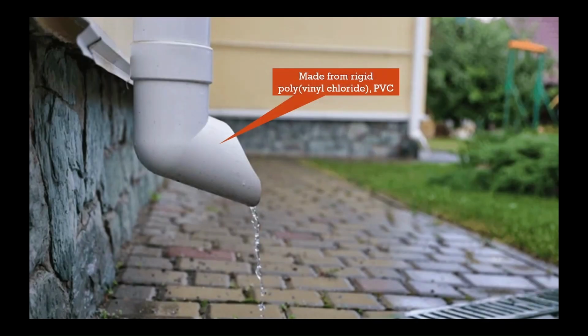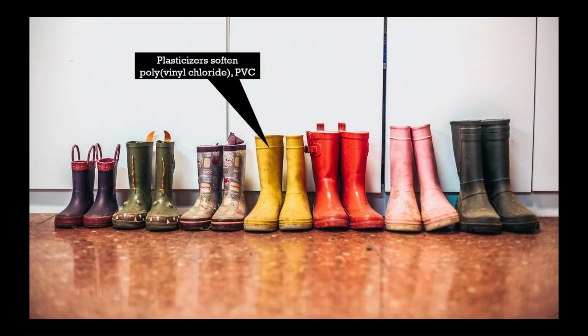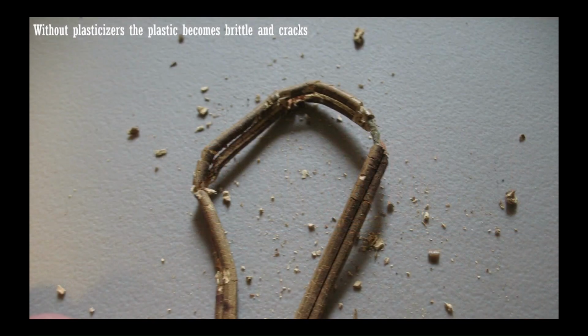Polyvinyl chloride, for example, is a hard, rigid polymer with a high molecular mass, commonly used in manufacturing drain pipes. However, when blended with a suitable plasticizer, it forms a flexible material used to make rain boots and doll parts. In some applications, plasticizers may gradually evaporate from the polymer, causing the material to lose flexibility over time. As this happens, the plastic becomes brittle and prone to cracking.